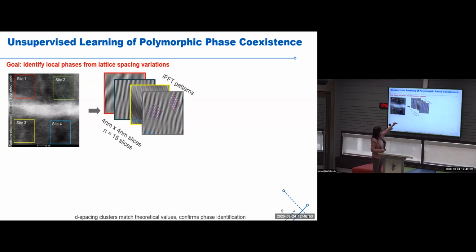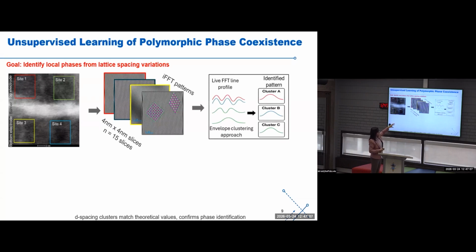So we took many slices from different regions, like in each region we took 15 slices, and first we did it manually. Then, because there are so many, right? We don't want user bias, so we used automatic lining, and then we used live FFT profile. And we can clearly see there are 3 different patterns. It is supposed to be one pattern because we are trying to grow a material which should be a stable phase. So one pattern should be there, but we can see there are 3 different patterns.